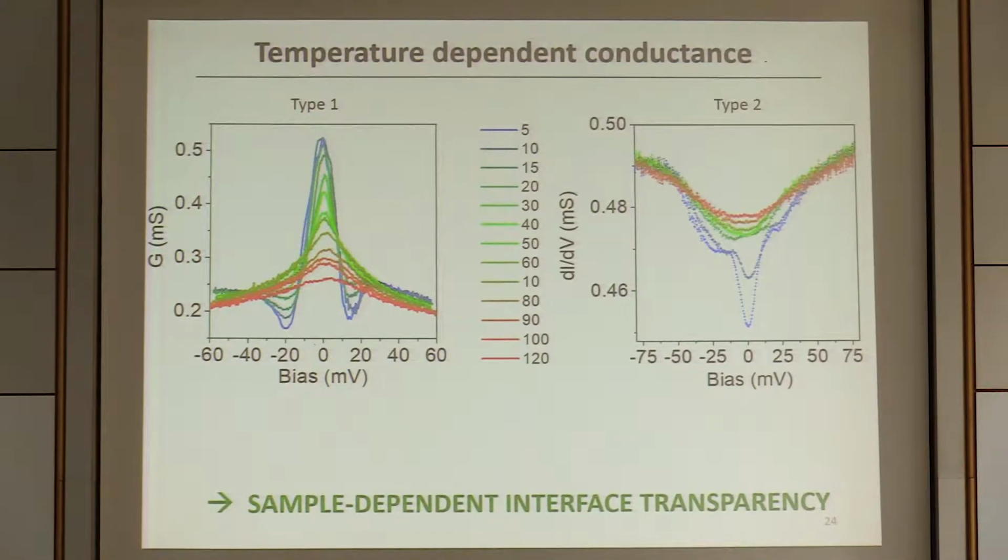So when we measure these samples, we have typically two types of behaviors that we see in these 3-point measurements. Sometimes we get this behavior in which you see this is the conductance. You have a bias for different temperatures, lowest temperature and then highest temperature. So this is about TC. And so you see either an enhancement of the conductance for bias which are comparable to the superconducting gap in YBCO, and this enhancement decreases as you get close to the critical temperature. Either you have the opposite, you have a decrease of the conductance at low temperatures, and then this thing goes away as you increase to TC. So looking at this from far, this looks like you have a highly transparent interface between a superconductor and a normal metal.